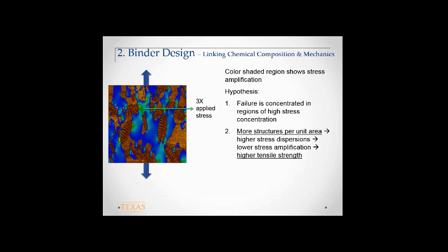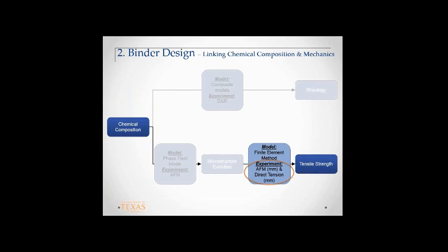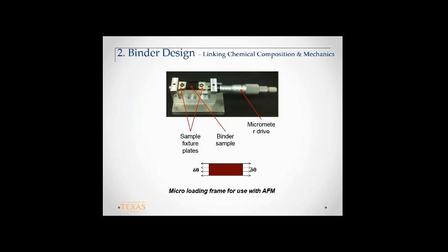The second hypothesis, we say that if you have more of these structures, and smaller structures, you have a better distribution of stress, which means these hot spots are not 3x, but maybe only 1.5x, but more distributed throughout the material. So you don't have very high local amplification, but more of a distributed amplification. So we take those two hypotheses and run experiments on an AFM to try it out.